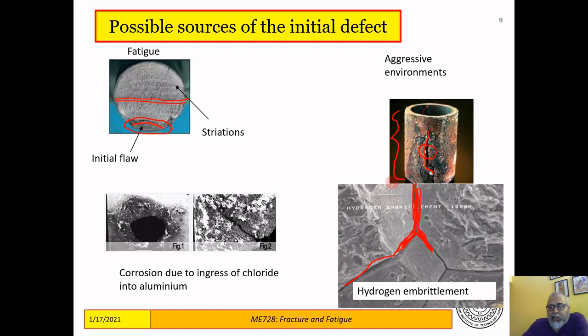Another example of aggressive environment is corrosion, which happens in, say, a saline environment. This is a corrosion due to ingress of chloride into an aluminium structure. What you see here, this whole feature, is actually the top view of this corrosion pit that had somehow developed in the material due to ingress of chloride. So this was the result of a chemical reaction that created the small pit, and then during operation a crack emanates from the small pit and leads to failure of the structure.